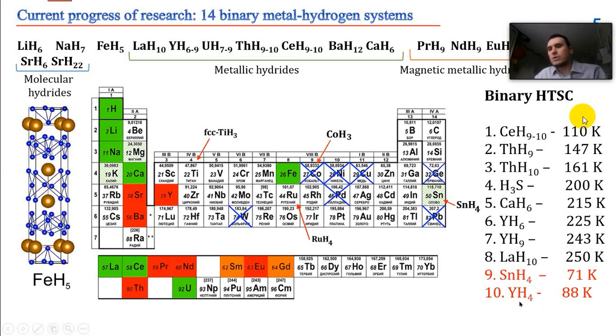It's interesting to note that yttrium H3, which exists and is stable at normal conditions, is not a superconductor. But when we add one hydrogen atom, it becomes a high temperature superconductor with Tc higher than many cuprates. So just one atom of hydrogen completely changes the situation and the properties of this compound. It makes it very unusual, very outstanding.